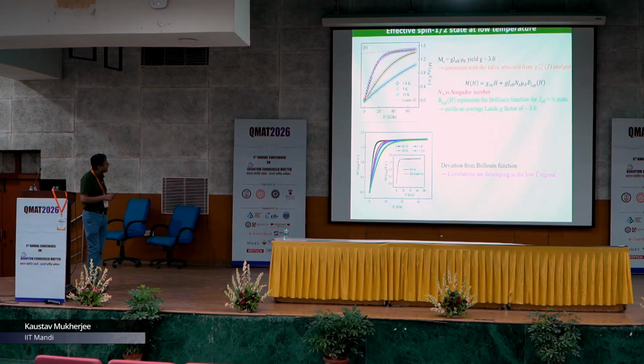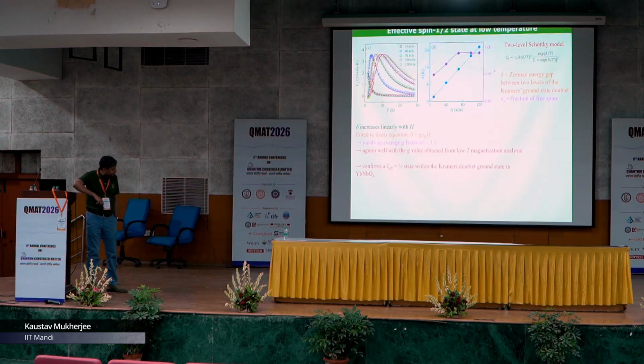We did the MH analysis, and what we found is that the fitting using the Brillouin function yields a Landé g value of around 3.1. We also did the MH curve at 400 millikelvin, and we tried to fit it with a Brillouin function, which is generally used for a paramagnetic state, and we saw that there is a deviation between the experimental curve and the fitted curve. So, it implies that correlations develop at low temperature.